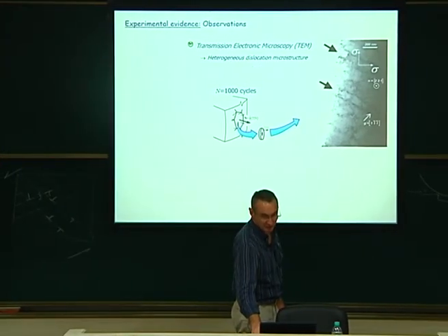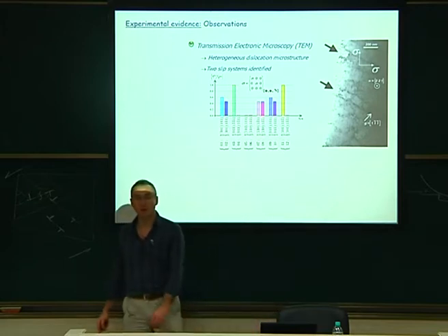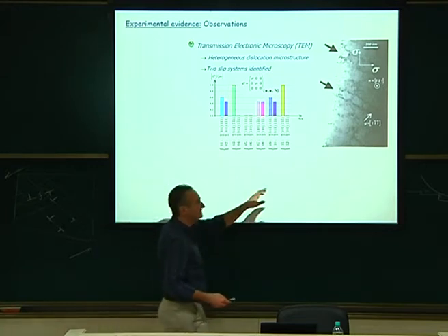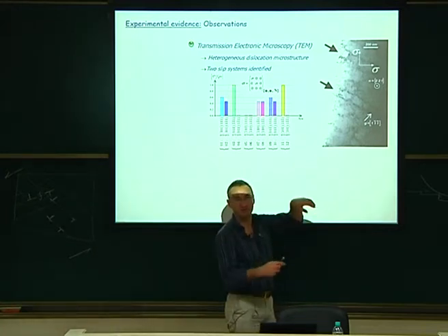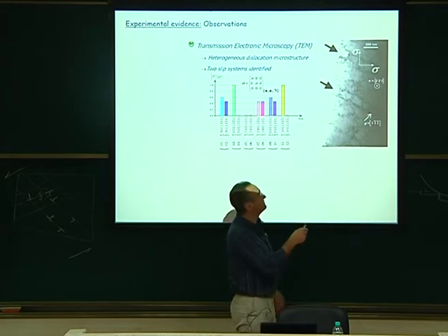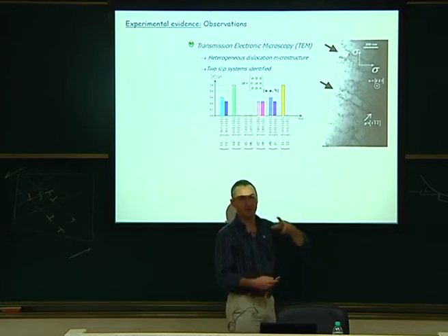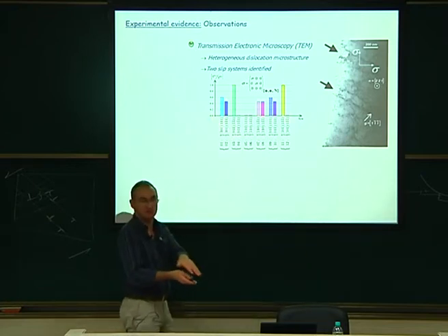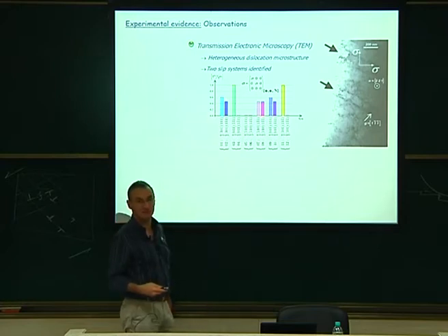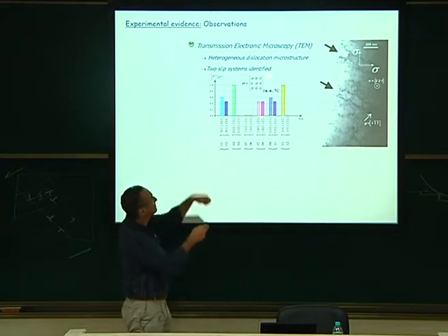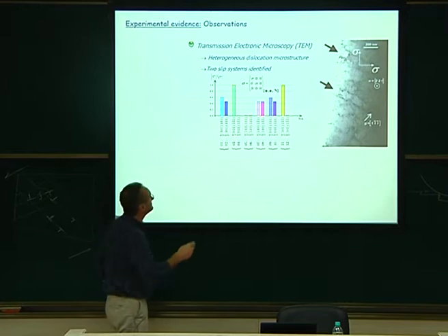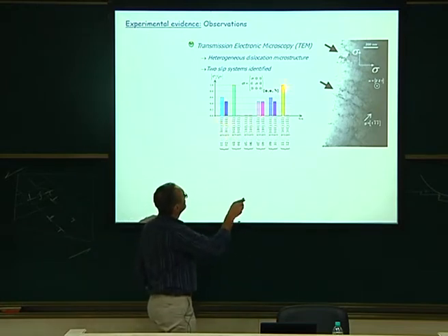Now, I pointed out here, if you investigate the whole set of dislocations that could be active due to the loading, to do that, what he did is that we have the loading conditions using FEM. Using TEM and EBSD, he was able to give the local orientation of the grain. And using the orientation of the grain, we can compute all the Schmid factors, so the resolved shear stress you have on the 12 slip systems of your specimen, if you apply 1 megapascal, if you apply this sigma. So the resolved shear stress looks like that, okay? And you see that some of the systems are heavily loaded, like these two, some are not loaded like that.